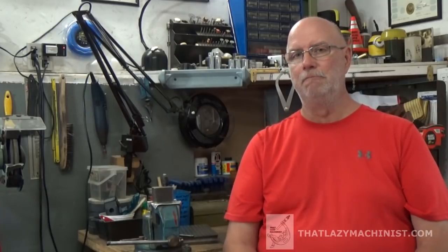And we're using the oil because our parts have to maintain accuracy, and the high carbon steels, even the medium carbon steels, are prone to cracking. The blacksmith doesn't have these problems. His main preoccupation is to cool that part down as quickly as possible. So dunk, pull out, steam, amounts of energy coming out of the part as quickly as possible. That's not what tool makers do.